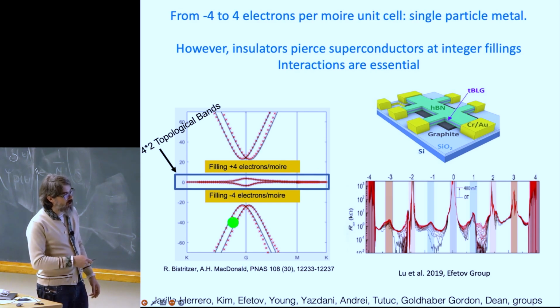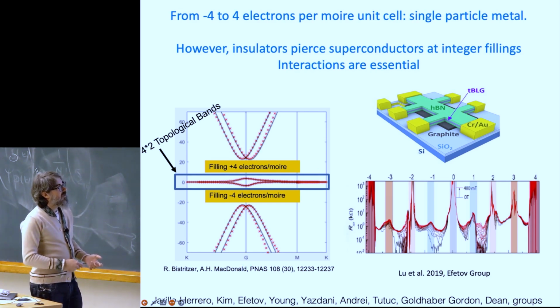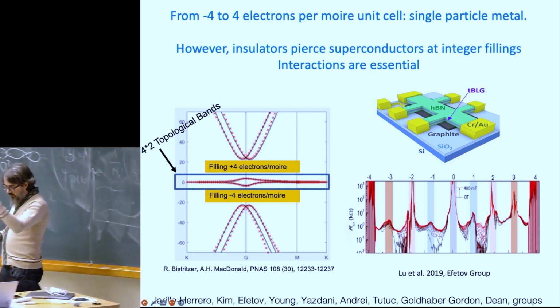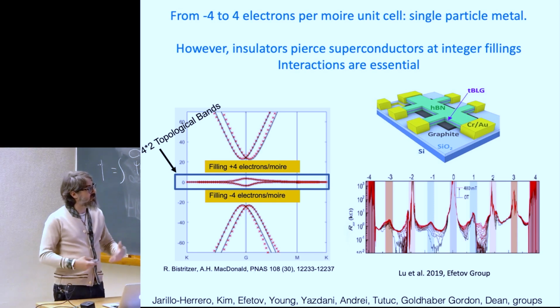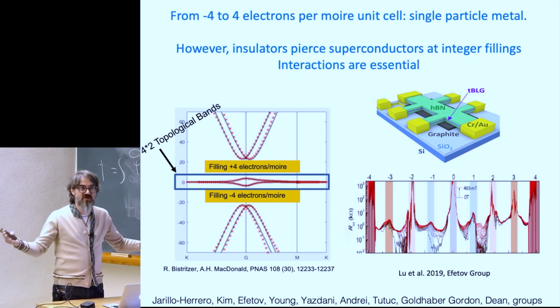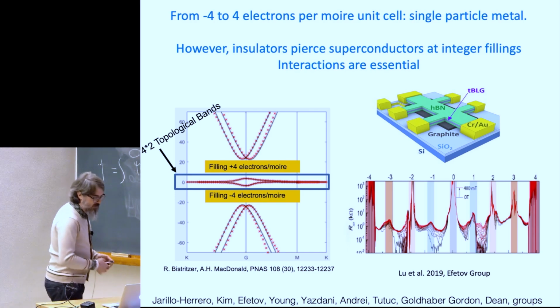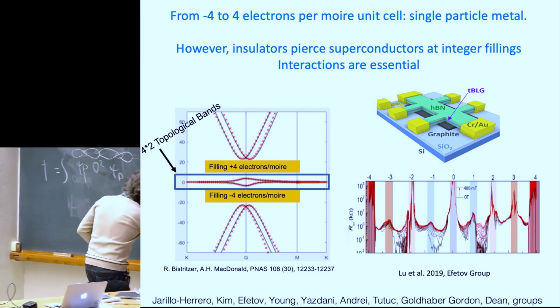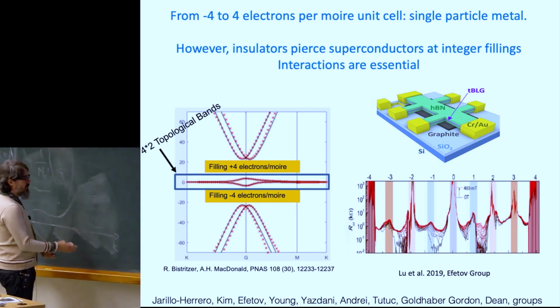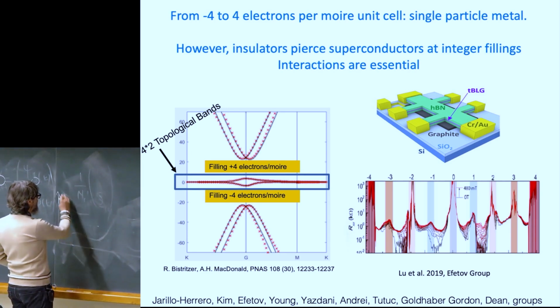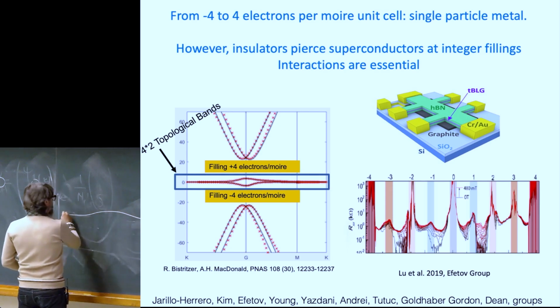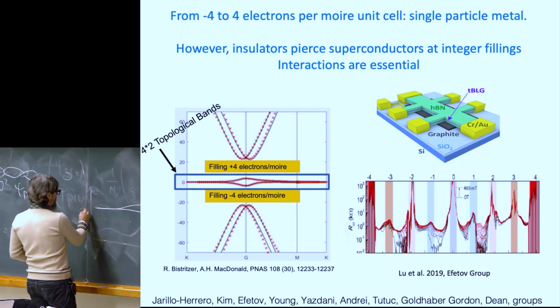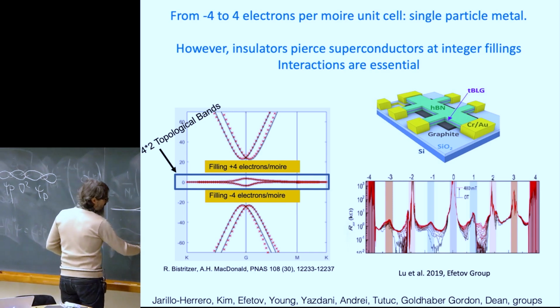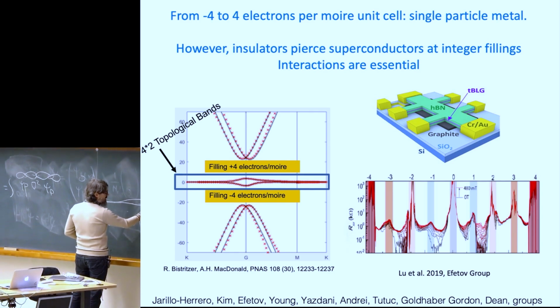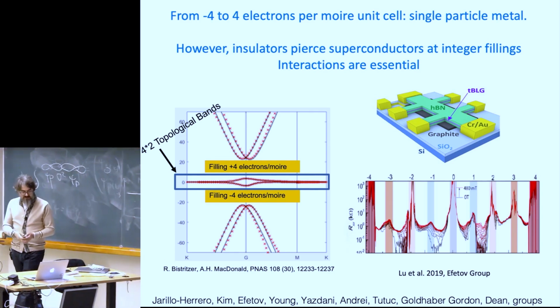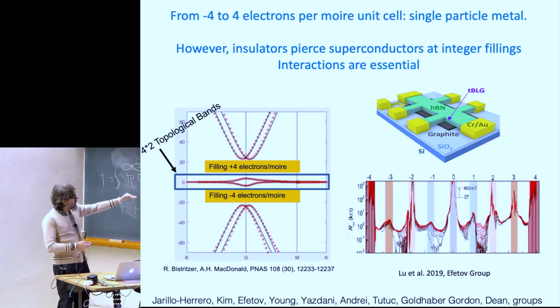But because this unit cell is so large in the Moire, you saw how the unit cell becomes large, then you can induce an integer number of electrons, or you can add a large number of electrons per this Moire cell, because 1 electron per Moire cell means 1 electron per 10,000 original graphene cells, and that's not hard to do. So now what happens here is that if I go between minus 4 electrons and 4 electrons, so I start doping, I can do it continuously with a gate, then let's just look at these bands. I can go, say, minus 3 electrons. At minus 3 electrons, I've doped it with 1 electron with respect to this gap, and then I'm here. And then the system would be a metal. It would intersect electronic states. In non-interacting physics, it would be a metal. Now you go to minus 2, even more, you raise the Fermi level, it would be a metal everywhere.